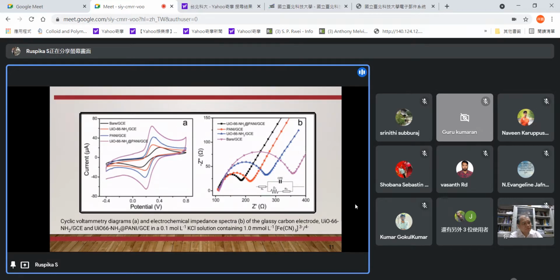And the bare GC has a relatively large electron transfer resistance of about 246 ohm, and for PANI, polyaniline coated on the surface of the MOF, shows 76 ohm, which indicates the polyaniline has electrical conductivity and can accelerate the electron transfer on the electrode.